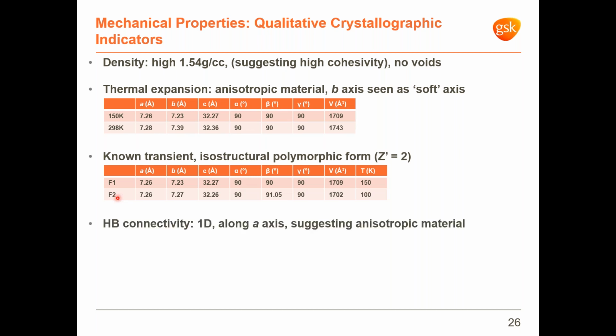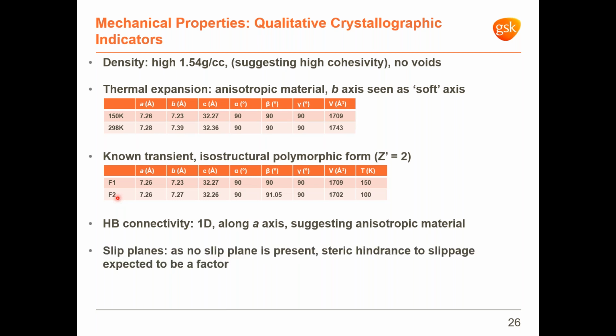Hydrogen bonding connectivity is also a useful indicator to identify potentially less compliant directions in the structure. In this case, we observe a 1D connectivity along the crystallographic A-axis. And finally, evaluation of slip planes. No slip plane could be identified in this case, and based on this, we can expect steric hindrance as a limiting factor towards slippage along most weakly bound planes.